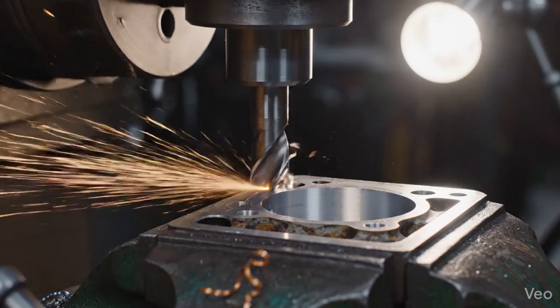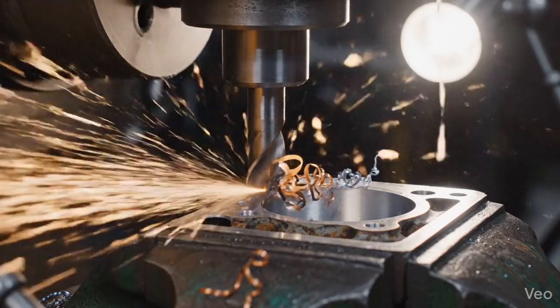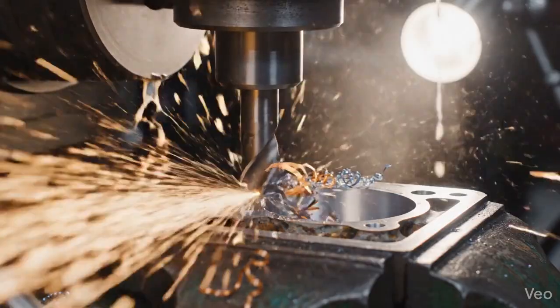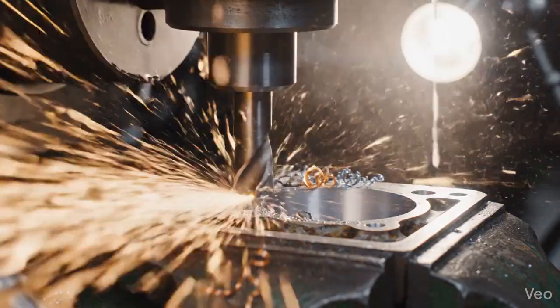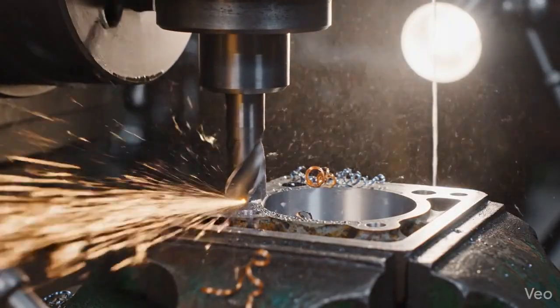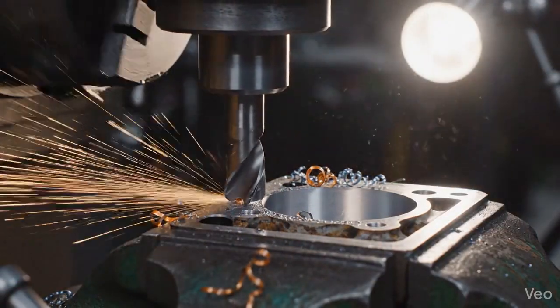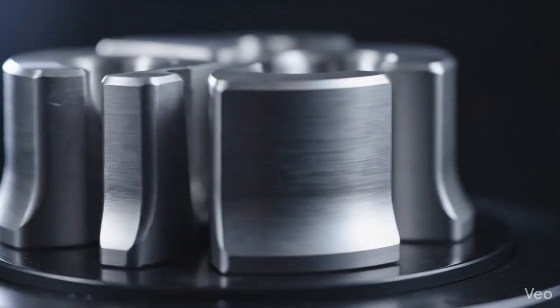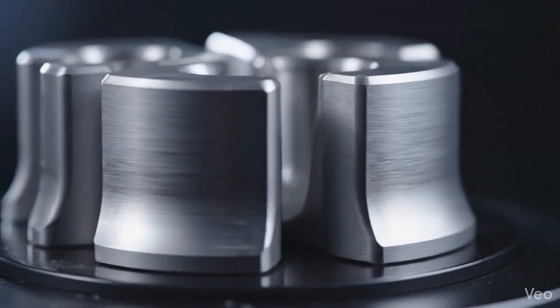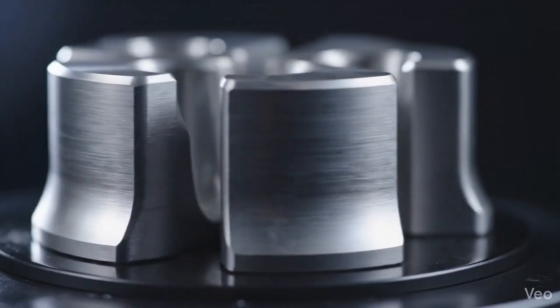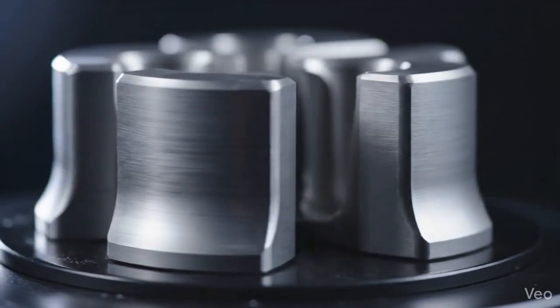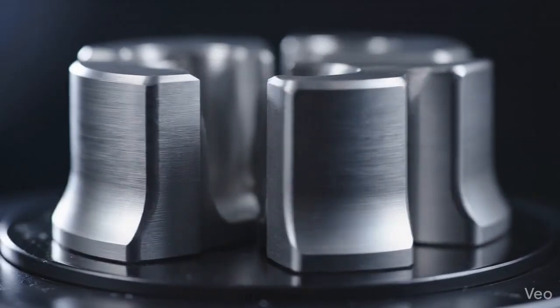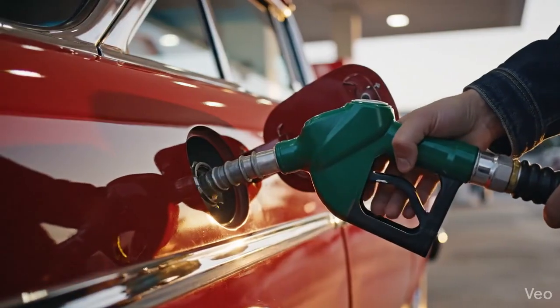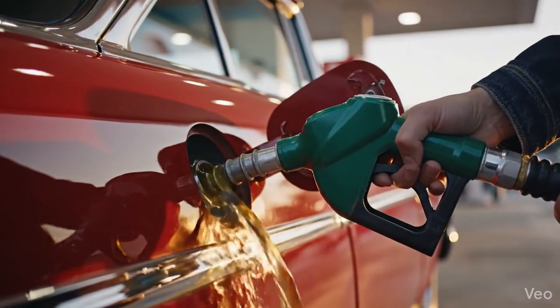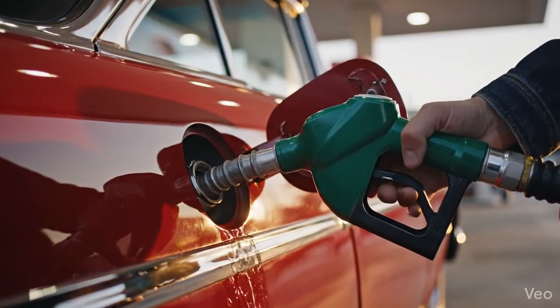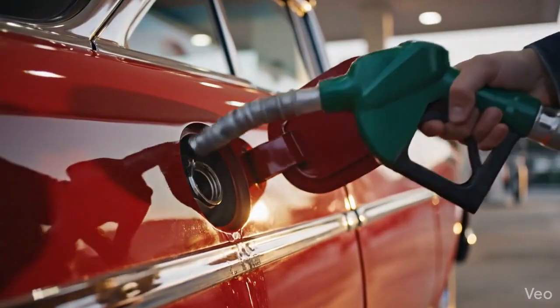The modification is well understood and not complicated for a competent machine shop. The original seat material is cut out on a bore mill, and hardened steel insert seats are pressed in under interference fit. The inserts are made from tool steel alloys that do not rely on lead lubrication, because the material itself is hard enough to resist the contact wear. It is a one-time fix. It is a direct consequence of a regulatory decision, removing something from the fuel supply that was never a mechanical problem as long as it was there.